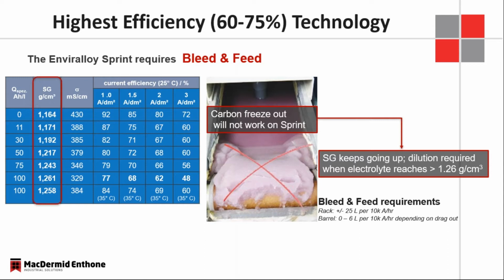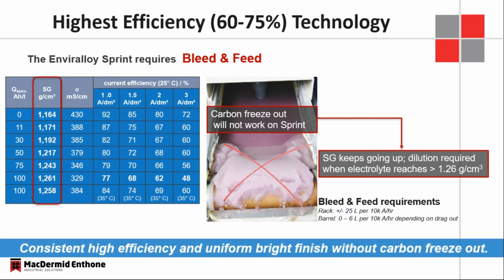As mentioned, carbonate will not freeze out on Sprint because of the potassium hydroxide. But we can monitor the solution in an overall sense, not just the analysis for potassium carbonate, but an overall sense of how much loading we have in that solution. And we can follow that by specific gravity. You can see on the lower portion of this slide, we talk about a rate of approximately, in a rack operation, 25 liters per 10,000 amp hours. And in a barrel operation, significantly less than that. We'd like to get down to, if productivity is high enough, where we don't need to have any reaction to a higher specific gravity. But if we do, we could be looking at as much as only 6 liters per 10,000 amp hours.